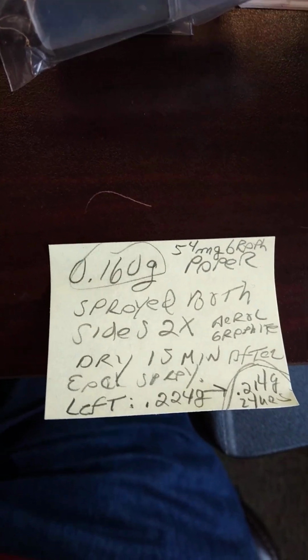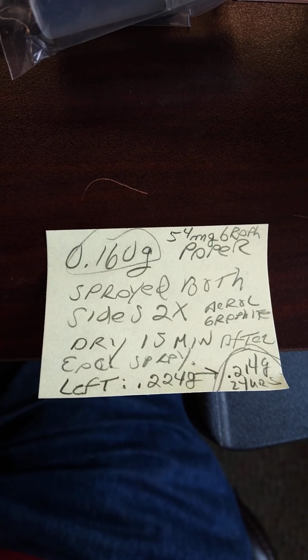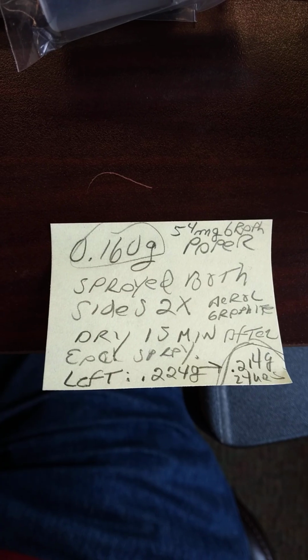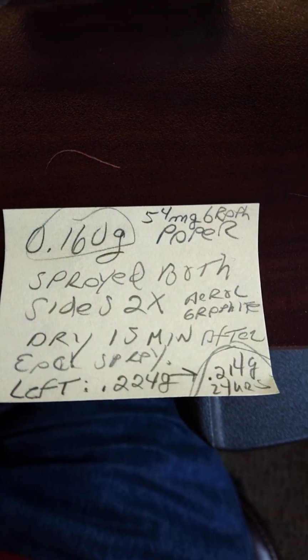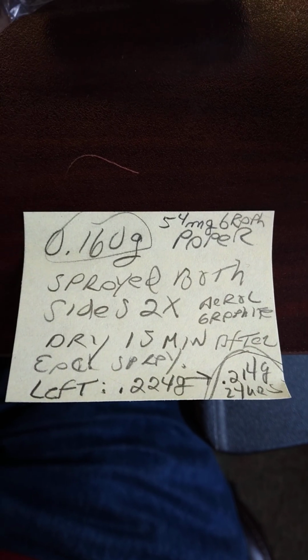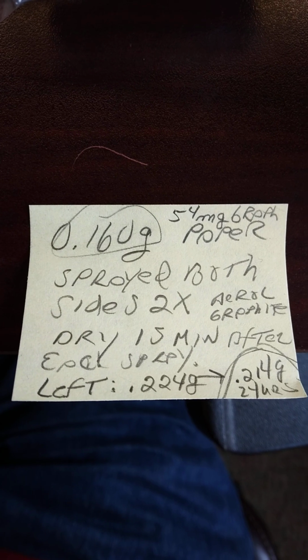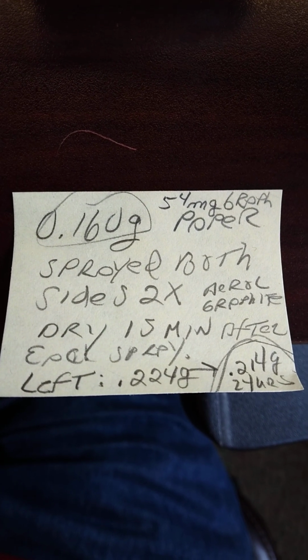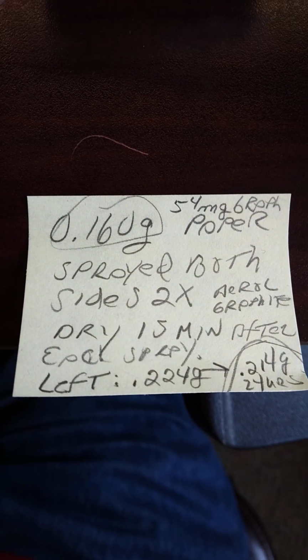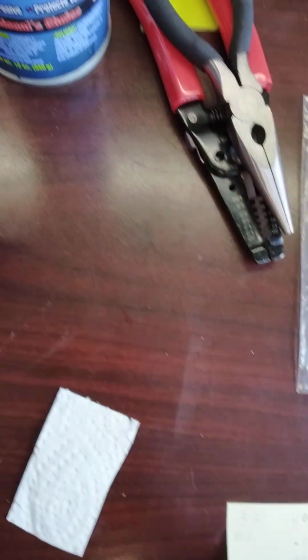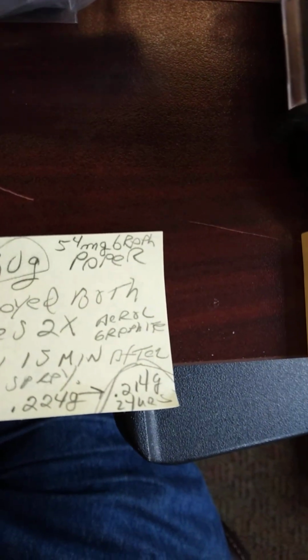Now, after being left alone for about 24 hours, when I left, it was at 0.224 grams. It started at 0.160. We left it overnight. The next day, constant mass reading 0.214 grams. So we have about 54 milligrams of graphite in principle on the paper. There will be some plastic binder, of course. But I like the resistance. This is, for our purposes, conductive enough. Now, we're also going to spray this on carbon paper, which is conductive, but that's another story, another experiment. So, according to my calculations, there's about 25% at best mass graphite on the front and back of the paper.